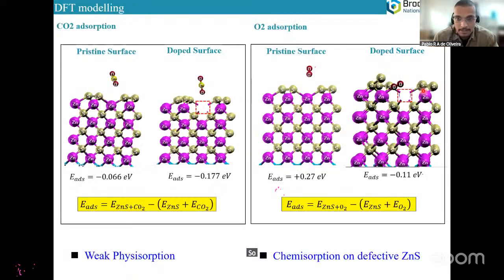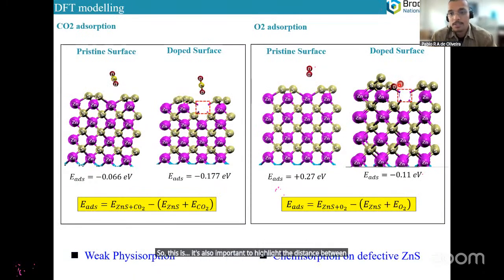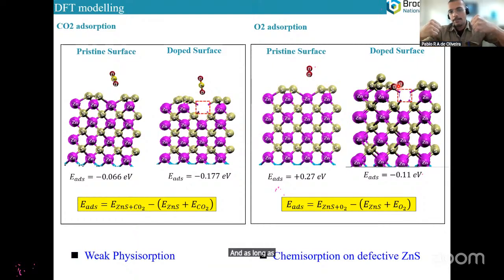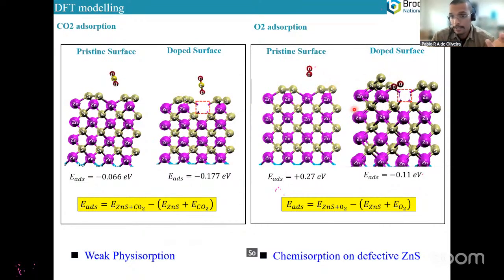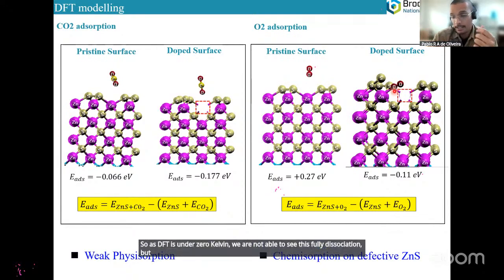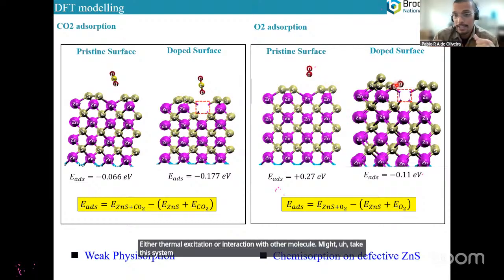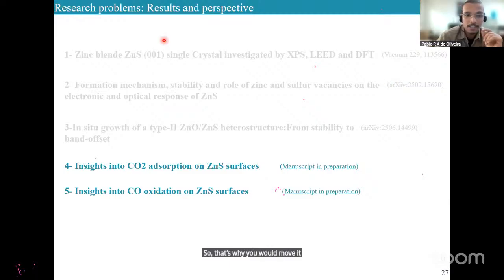So this is also important to highlight. The distance between these oxygen atoms has increased. It's typically 1.22 angstrom, and after the adsorption here it is like 1.4. And as long as the bond length increases, it might indicate that the system is going to dissociate. As DFT is at 0 Kelvin, we are not able to see this full dissociation, but it might indicate that either thermal excitation or interaction with another molecule might take the system to dissociate and be used for another reaction.